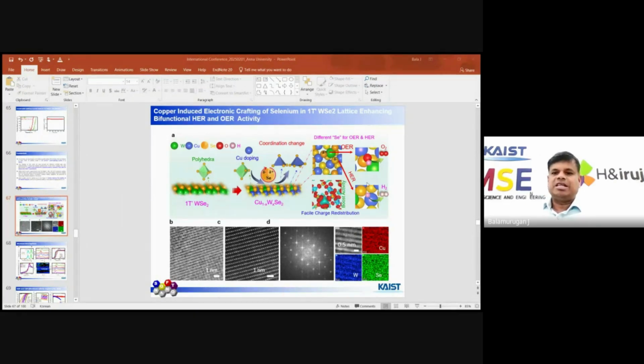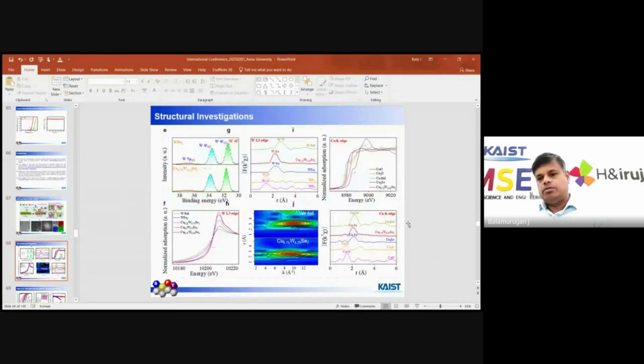You can see here selenium is the active site, in the copper tungsten selenide, because when you increase the copper loading, the performance is enhanced. Another thing: there is no report of such selenium active sites. Usually the metal is the active site for OER and HER, but in our case we predicted the selenium is the active site, an anionic active site.